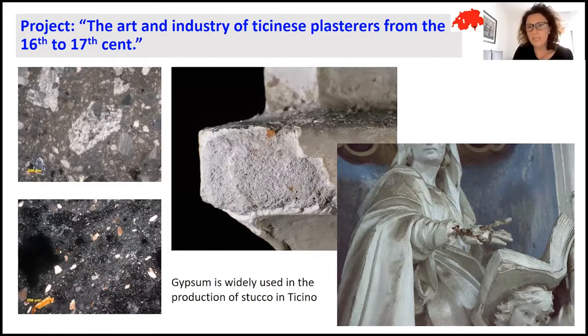Gypsum was widely used in Ticino for the production of stucco. In particular, if you listened last week to the lecture of Giacinta Gian, she already presented this project, the art and industry of Ticinese stuccatori. We see that in this period, the techniques of production of stucco normally followed a particular recipe, in which the ground layer of the stucco was made of a mix of 2 binders, lime and gypsum mixed together, with a low presence of river sand aggregate. And the finishing layer of the stucco is made of only lime and marble powder, in order to give the final statue an aspect similar to a marble statue.